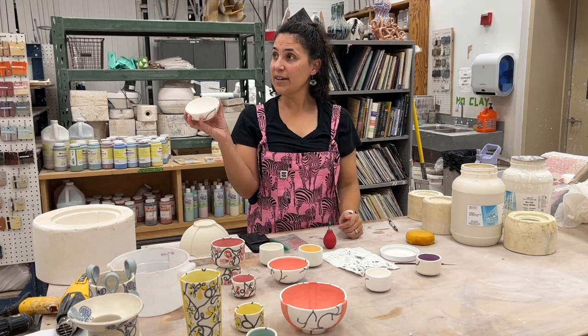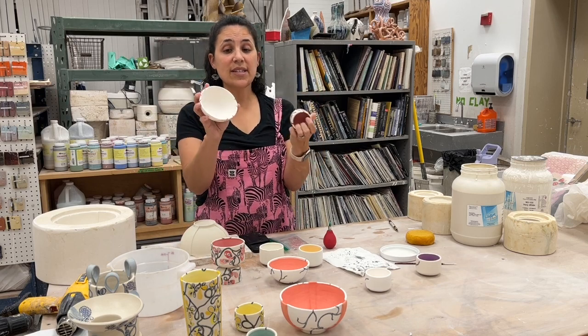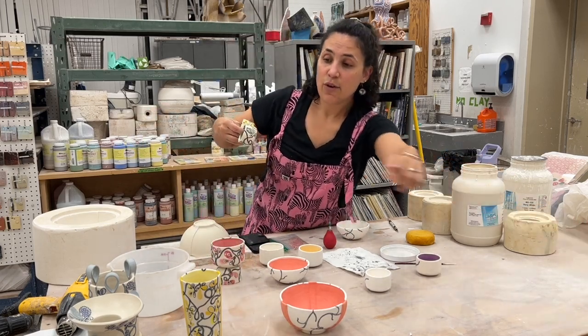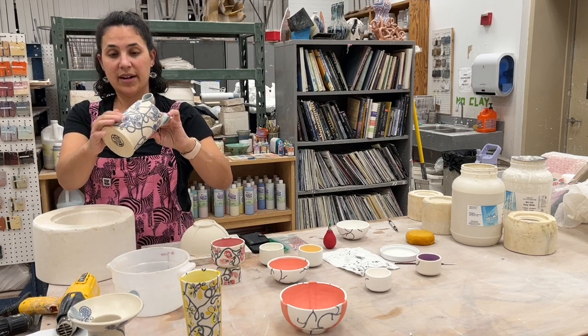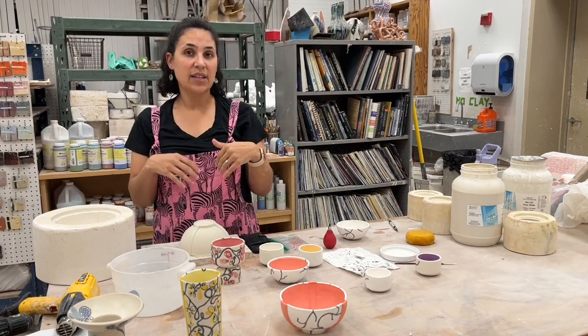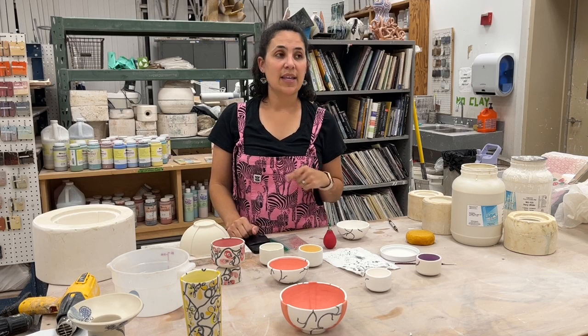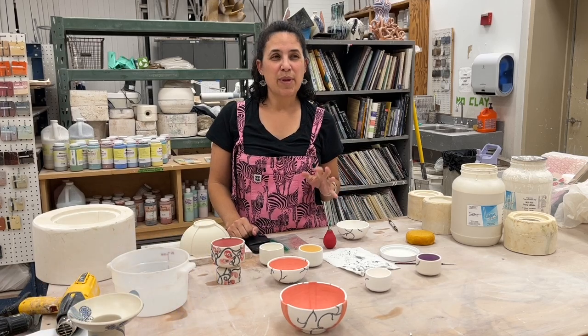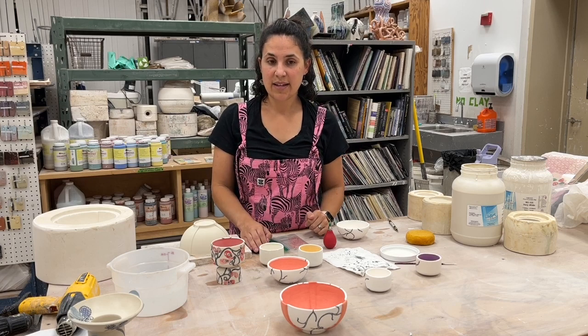So this would get finished and fired and then it's done. Do you put a clear glaze over it for the last firing? Yeah — it just gets placed with that matte clear on the inside, but all of these are fired on the outside unglazed. You can feel those versus the glazed ones. I leave it unglazed on the outside because that porcelain clay is just so nice and buttery soft when it's been sanded. With the B mix I feel I can't get it quite as clean when sanding, so that's why I'll glaze the outside of the hand built work.